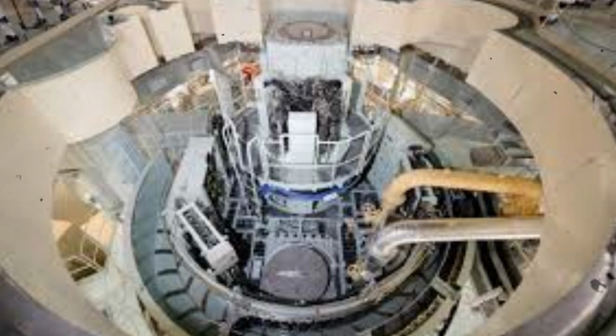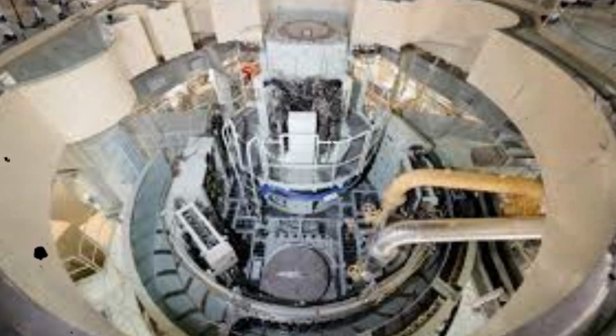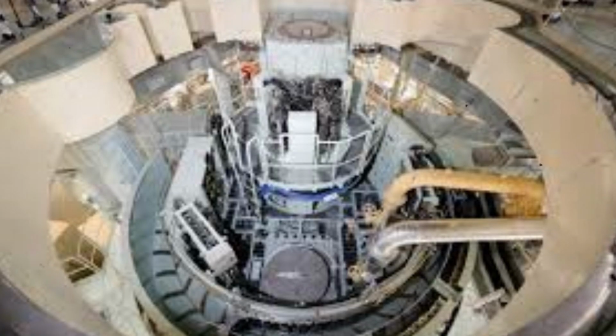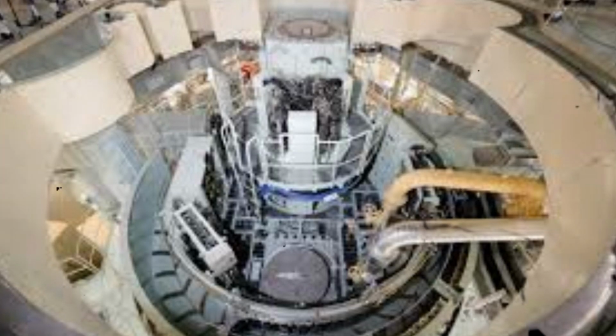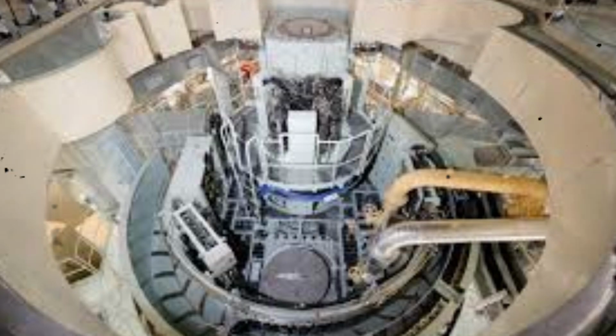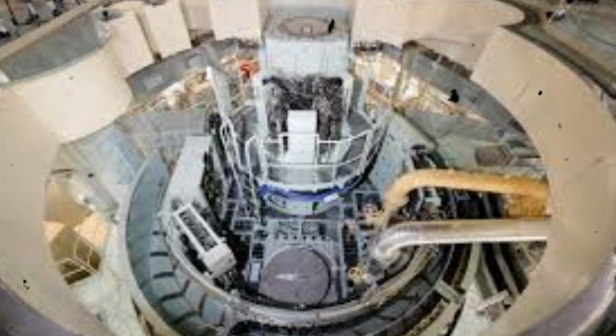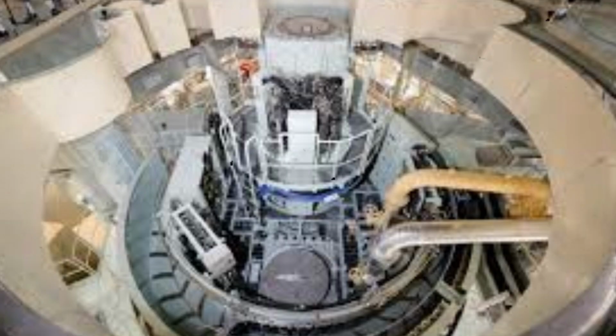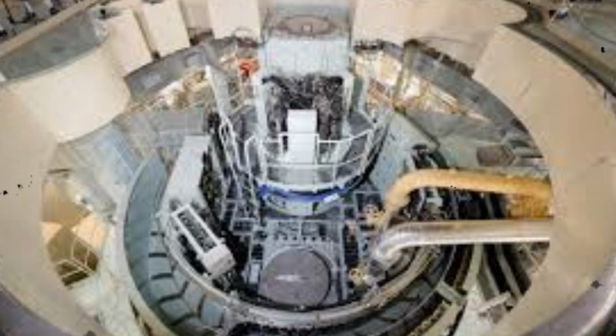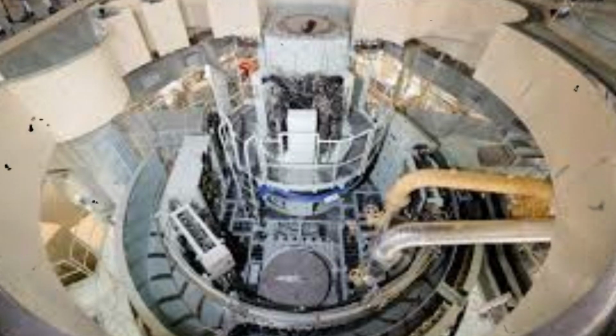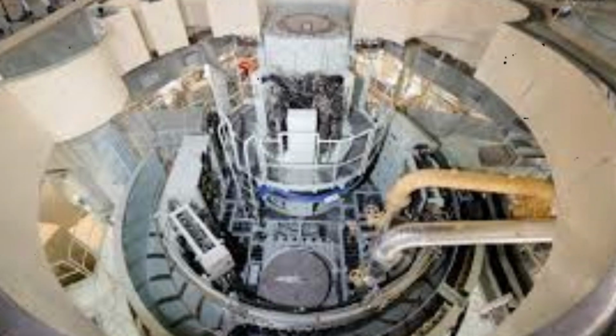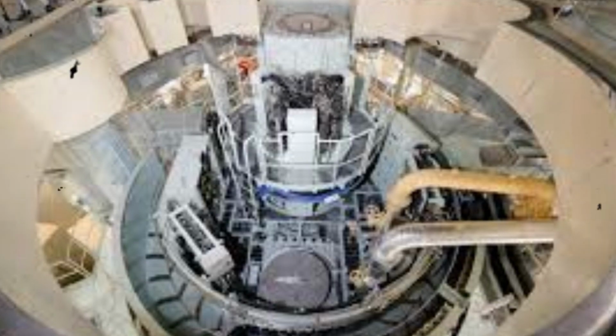Chemical analysis of the accumulated compounds confirmed that oxidation reactions had proceeded to completion for sodium that had sufficient contact time with atmospheric components. Compounds closest to the leak point showed higher concentrations of incompletely oxidized sodium, indicating that reaction rates were limited by oxygen availability rather than reaction kinetics in regions with high sodium concentrations.